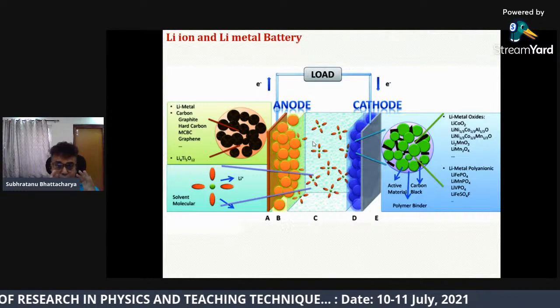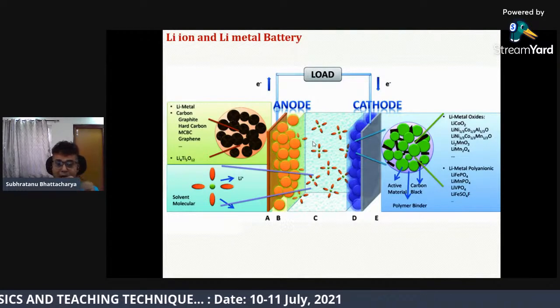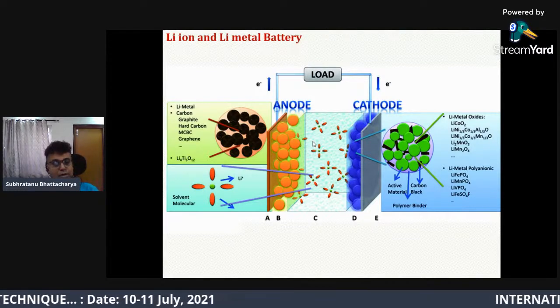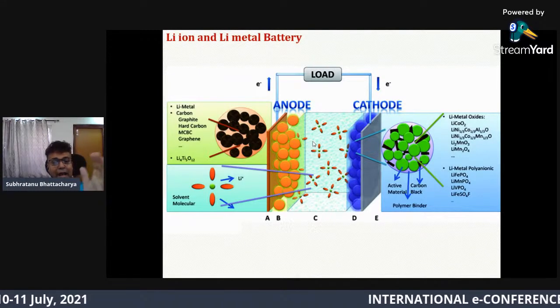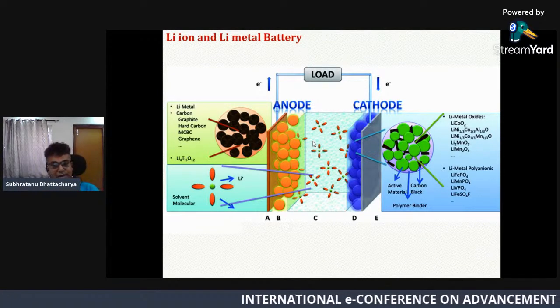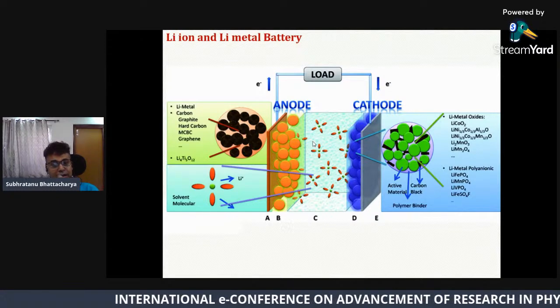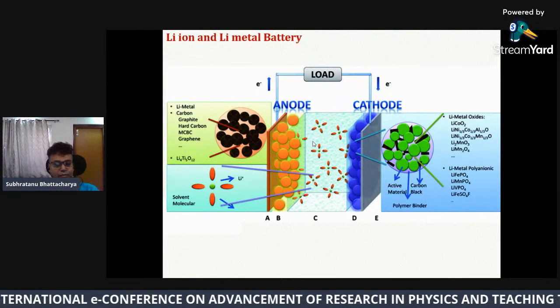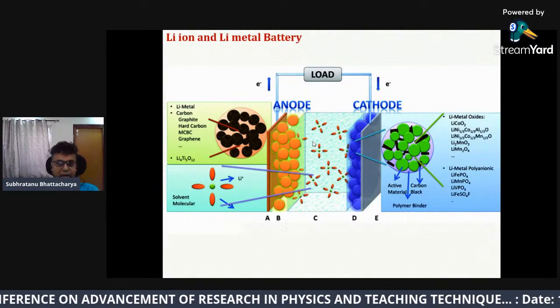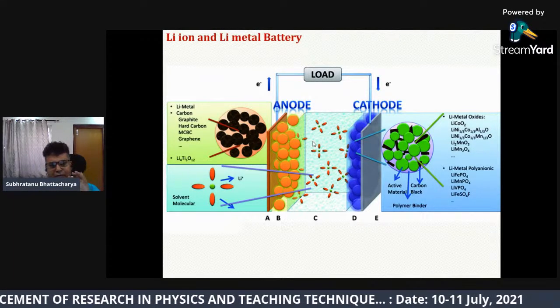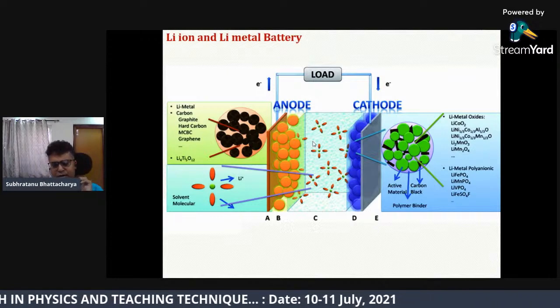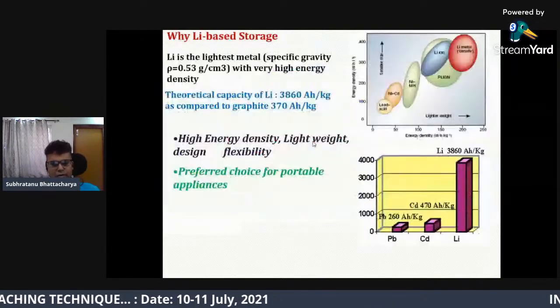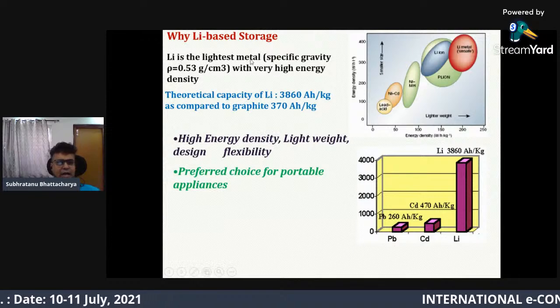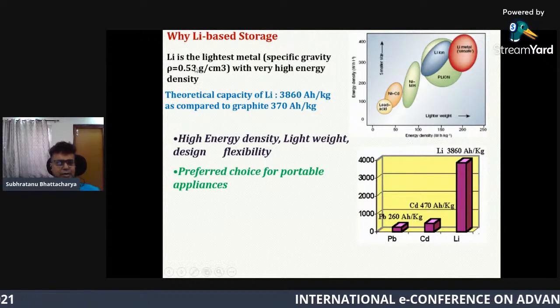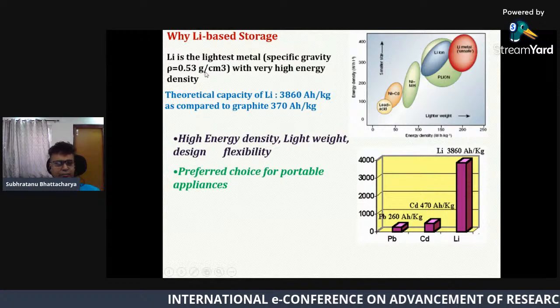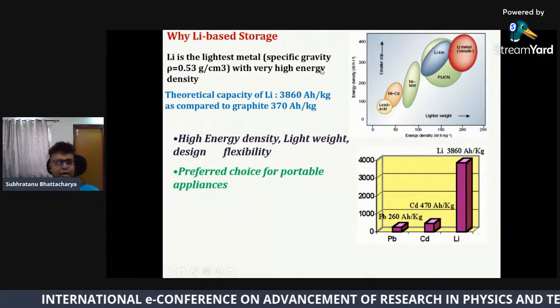graphite. But what if we use, like in a primary battery, lithium metal as anode material? What is actually restricting the use of this lithium metal? That is the focus of the research nowadays in lithium batteries, because this graphite actually has a theoretical capacity of only 372 mAh per gram. Lithium is the lightest metal with a specific gravity of 0.53 gram per centimeter cube, and with a very high energy density.